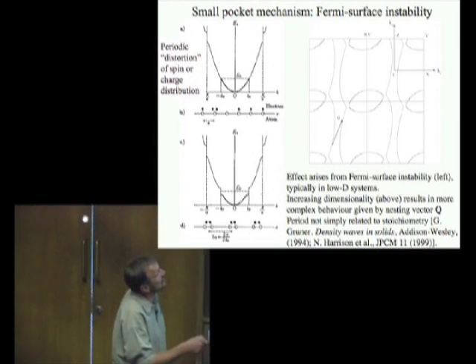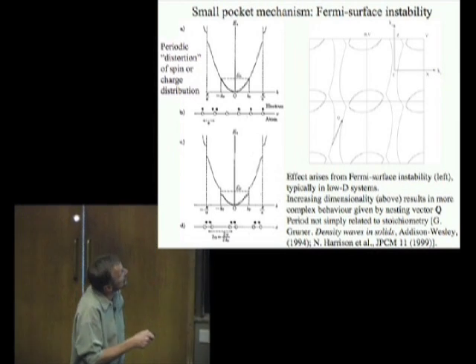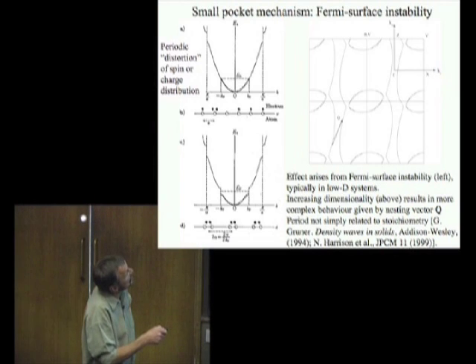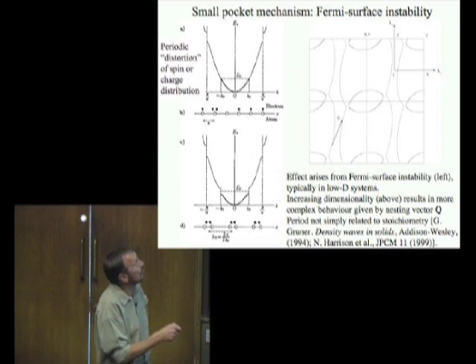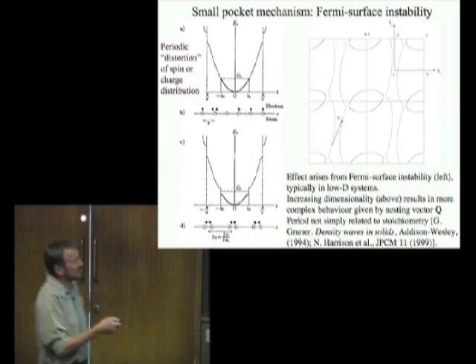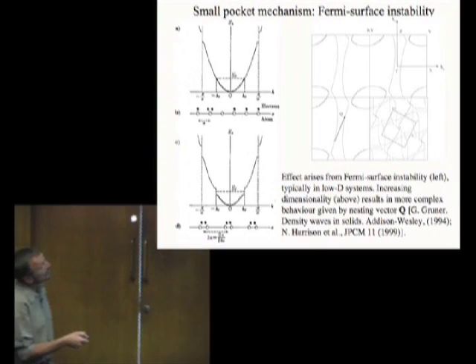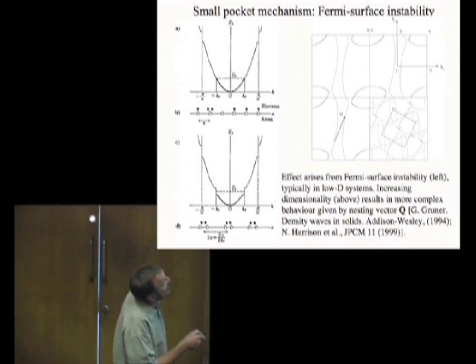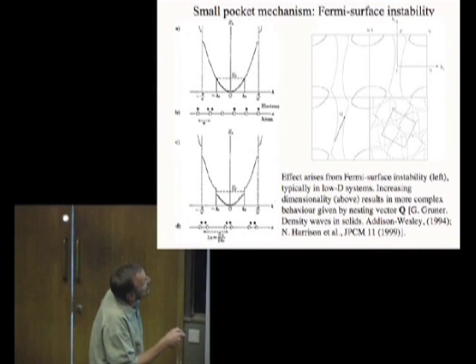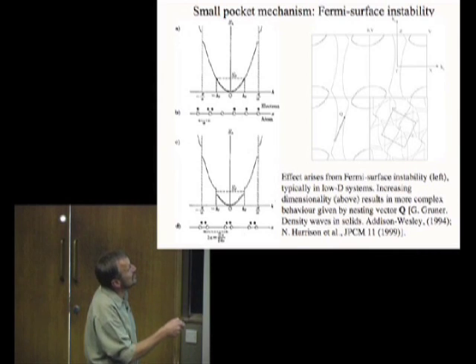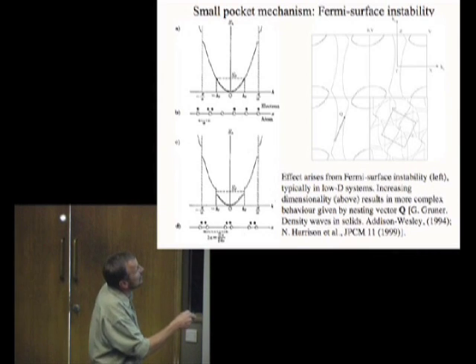This is a Fermi surface of an organic metal that we looked at a few years ago. Here it has two parallel sections like that. It turns out that if you can get a distortion that has a wave vector, a periodicity, in other words a 1 over periodicity, which can map one part of this onto the other and wipe out quite a lot of states, the system can lower its energy that way. And this is what happens. Once you map this onto here, the system can lower its energy by wiping out all of these states. It's opening up this gap.